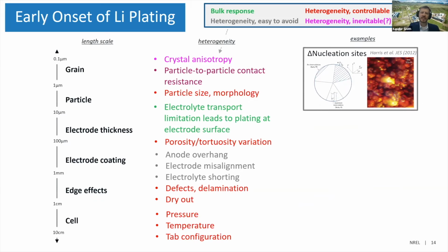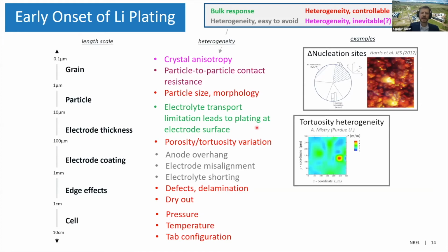And so with this, you can kind of see in optical images that there's localized regions which are preferentially intercalated. The brightest spots are the ones that are intercalated the most. And so there's definitely some heterogeneities here. And indeed, if you continue with these optical images and further into the charging, you definitely see lithium is plated preferentially at certain regions in this electrode. These are things that we're working to understand under this program to see how we can best suppress this. The Newman model just gives us the viewpoint of the electrode thickness heterogeneity that I described on the previous slides. Some other factors across the electrode coating, either at the hundreds of microns, maybe to millimeter scales, there's going to be variations in both porosity and thus tortuosity across the electrode.